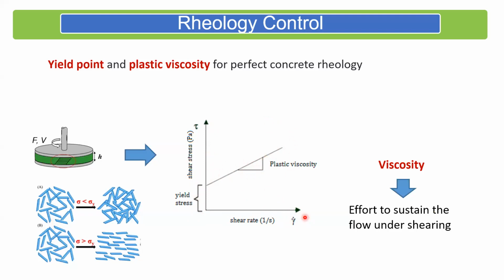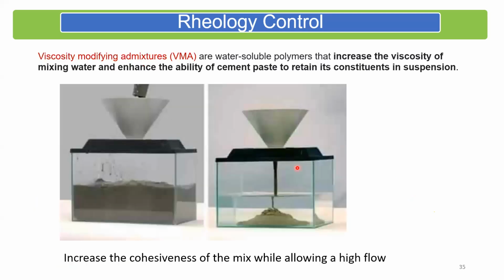And the slope of this shear stress versus shear strain rate is called plastic viscosity. The more the plastic viscosity, the more viscous the material. That means it would take more effort to keep the flow going. So there is one thing, which is to initiate the flow. The other is to sustain the flow. How much effort would I have to put to sustain the flow? So these are things that we have to control when we are talking about producing concrete, which we would want to engineer. And the final thing that we also realized is that there has to be something called cohesiveness of the mix, where once it starts flowing, I want to hold all the ingredients together.